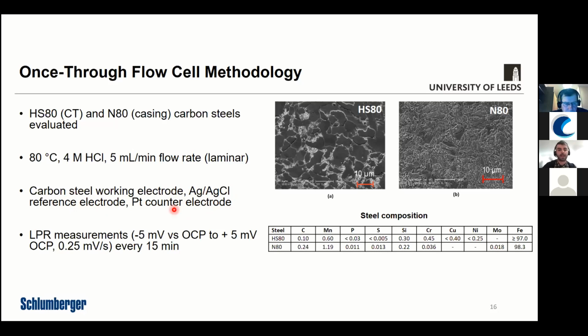And to assess how effective the inhibitor is, we would complete linear polarization resistance measurements every 15 minutes. So one of the challenges with LPR measurements and any electrochemical measurements in such high strength acid environments is that the currents are so extreme that if you polarize too excessively, particularly when you've got an inhibitor film, you can fundamentally change the properties of that film by the electrochemical measurements that you're completing. So we deliberately scanned over a very narrow range relative to OCP, so -5 millivolts to +5 millivolts relative to the open circuit potential, so that it didn't influence the film as a result of any of the measurements we completed.